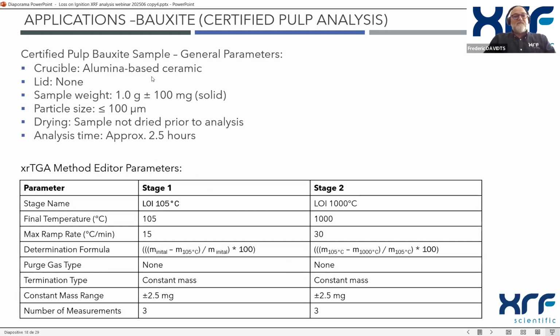Sometimes you need a higher temperature, and of course, it has an effect on the cost of the process. So for the conditions of the thermogravimetric analyzer, we use alumina-based ceramics. We work with 1 gram, ground below 100 microns, and we start with the non-dried sample. The analysis time will last about 2 hours and a half.